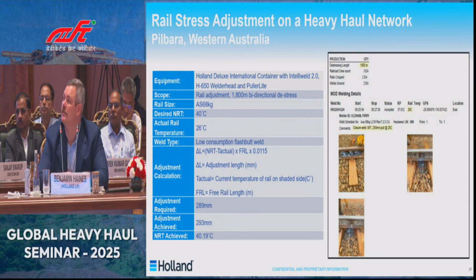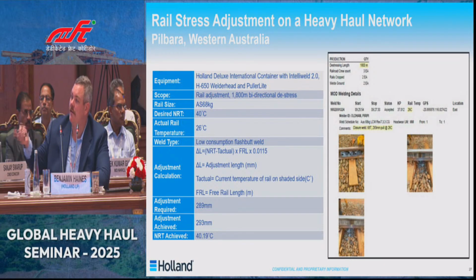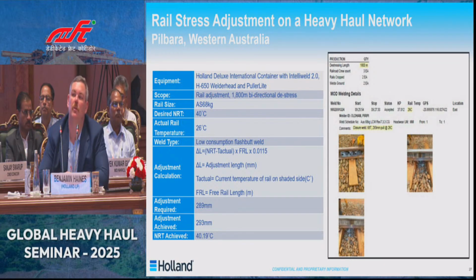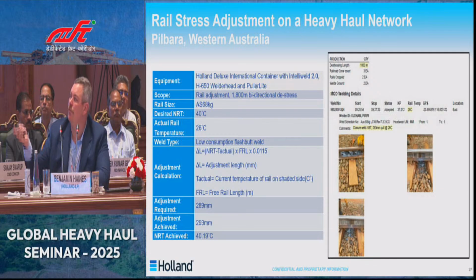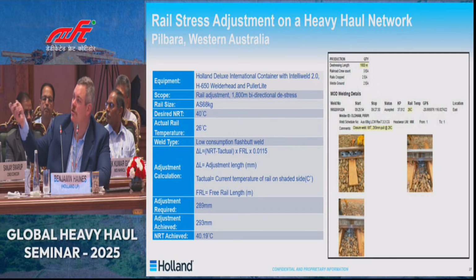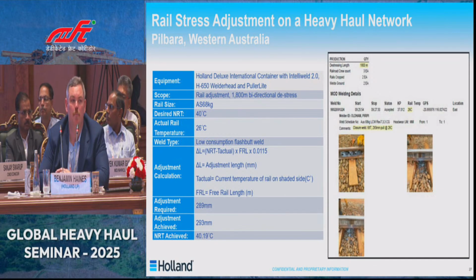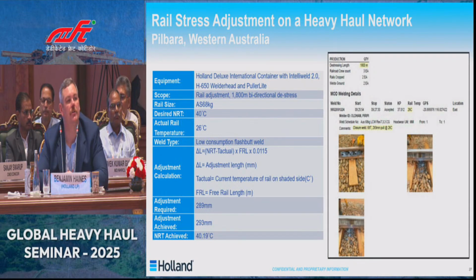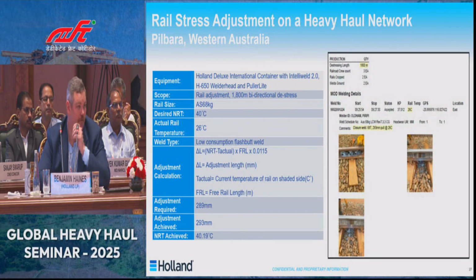You can see it has a number of automated inputs that come directly from the system, but also inputs from the operator. So we can put in the de-stressing length that we've done, the number of people used in the crew, the number of rails that we cut, and how many rails were ground. In this particular case, 2, because when we cut the track, we found that the original rail was laid at a lower temperature than the NRT, therefore it was rail deficient.